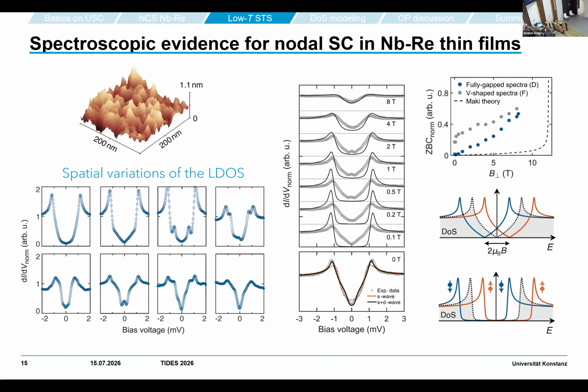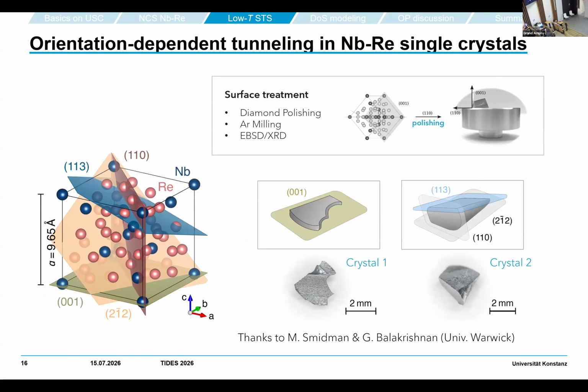So this is all indications that we do have an order parameter symmetry that is not simply S-wave. However, we have this mixture, these granular films where we might have different orientations that we are probing. So to learn more about what is going on, we then went to single crystals, and we probed the single crystals in different crystalline orientations.